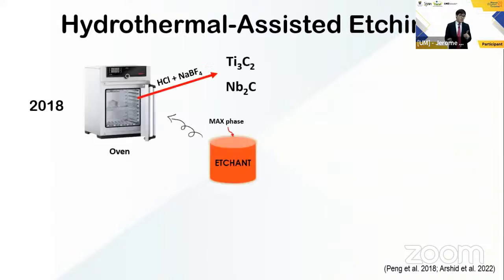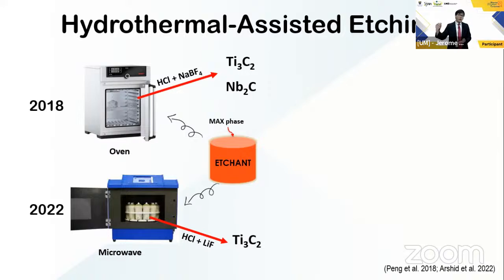Four years later, in 2018, hydrothermal assisted etching was introduced using a conventional oven to make titanium carbide and niobium carbide. This was performed using in situ HF. And fast forward four years, in 2022, Sunway University, Malaysia introduced microwave, firstly utilized in hydrothermal assisted etching to make titanium carbide using in situ HF as well.